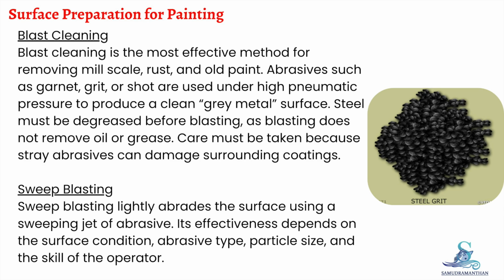That brings us to blast cleaning, the most effective method. Blast cleaning removes mill scale, rust, and old paint using abrasives such as garnet, grit, or shot under high pneumatic pressure. This produces what we call a clean gray metal surface. It is important to remember that steel must be degreased before blasting, because blasting does not remove oil or grease. Care must also be taken, as stray abrasive particles can damage surrounding coatings.